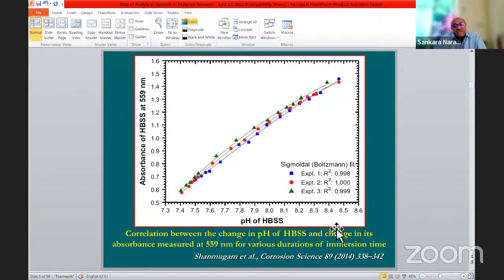Suppose somebody wants to monitor the corrosion behavior of magnesium in a sodium chloride medium. Sodium chloride is highly corrosive. So if you put magnesium in a sodium chloride medium, the pH might rise up to 9.5 to 10 sometimes. So we cannot use phenol red as an indicator for that because the limitation is only 8.4. So we cannot measure the absorbance beyond that point. So we have developed another similar method using a universal indicator. Instead of phenol red, we have used a universal indicator, and that is also published in a journal.